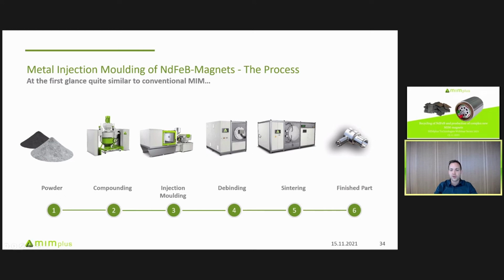These binders are first partially removed by the debinding process, and then only 1/3 of the binder is still in the part. Then the thermal debinding and sintering process follows, where the residual backbone binder, which is still in the part, is decomposed completely, and then in the sintering, the open porous structure is transferred into a 100% metallic part. There is no organic carbon anymore in the part, and it's nearly 100% dense. It means we have a density of larger than 96% in general.